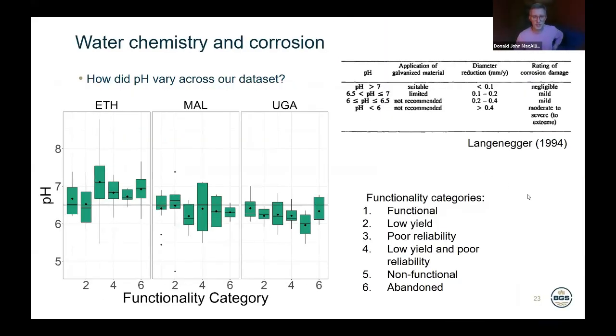This is just the high-level results that we got, and the plot here shows the pH values across the 145 sites in the three countries. It's shown against functionality categories, but I won't go into that in any real detail today. The main thing to point out is that generally pH is quite low across all three countries, and you'll notice in Uganda in particular, almost all of the sites had a pH less than 6.5. So by that standard, in Uganda almost all sites are at risk of rapid corrosion. In Malawi and Ethiopia there's a bit more variability, but there's still a significant proportion of sites with a pH value less than 6.5.